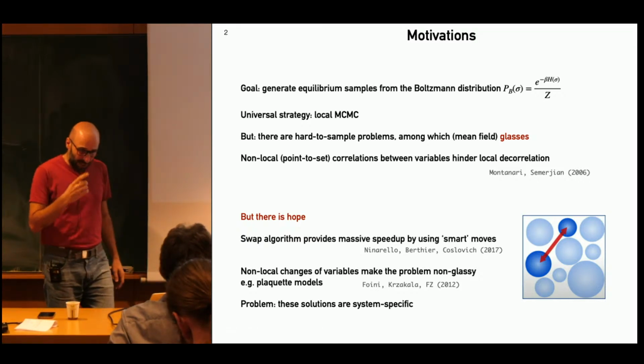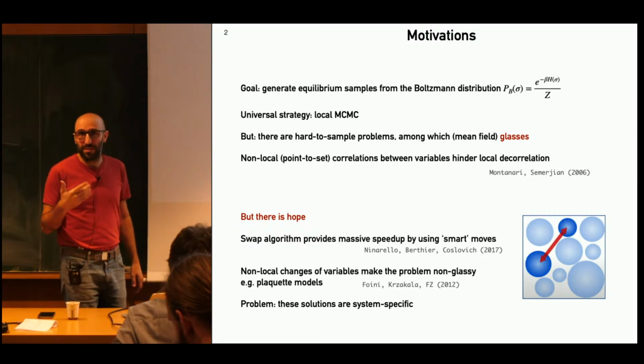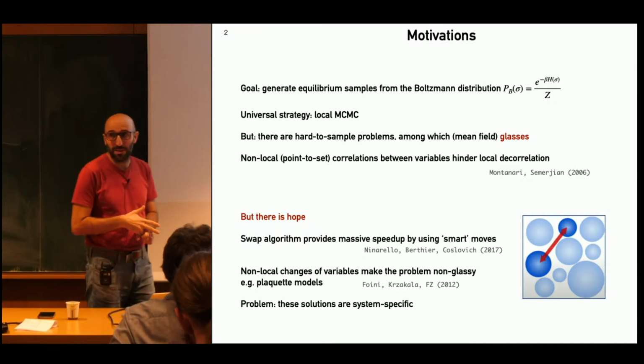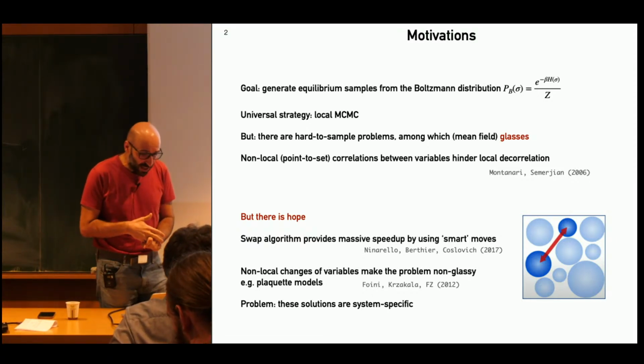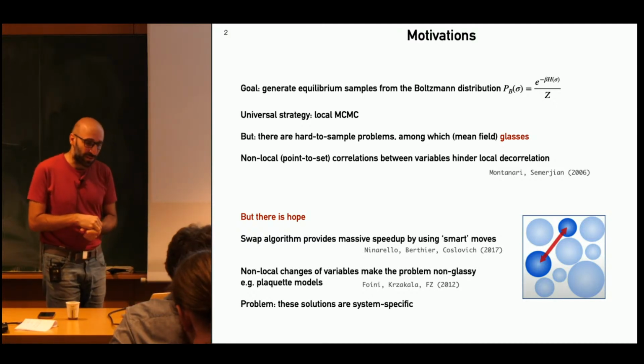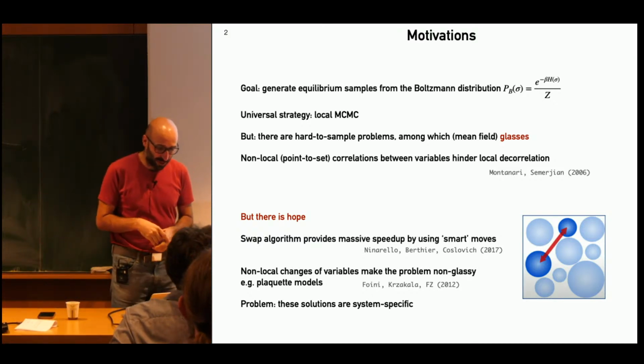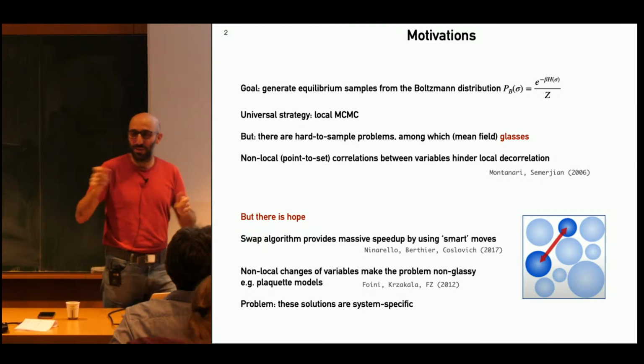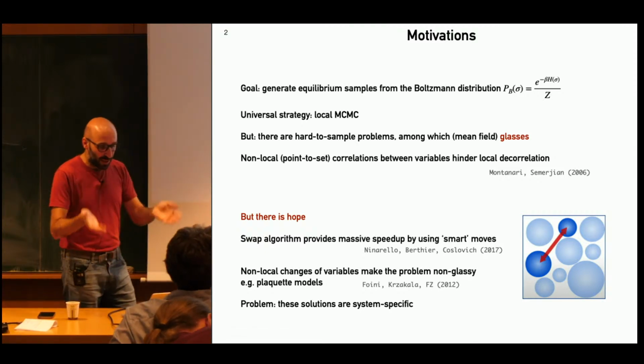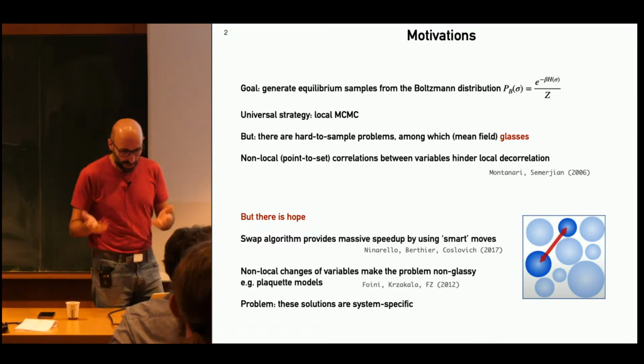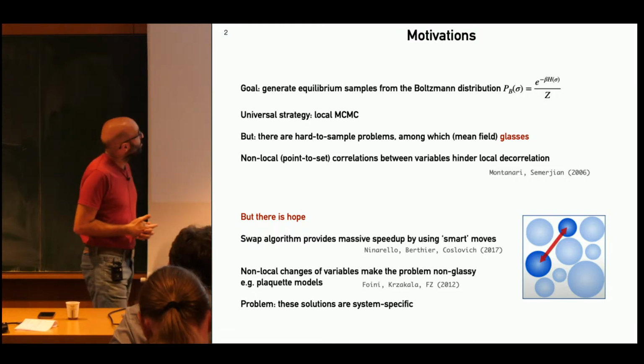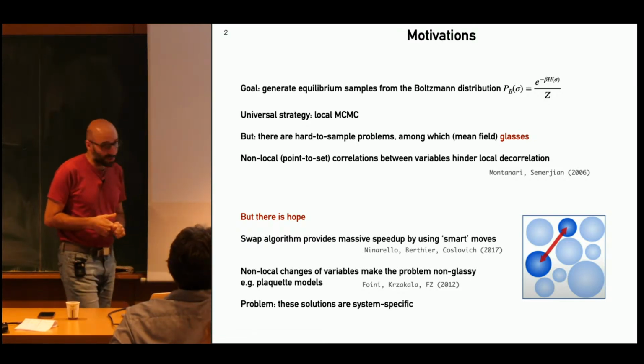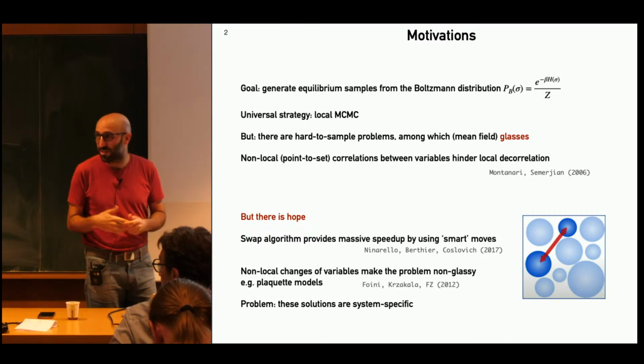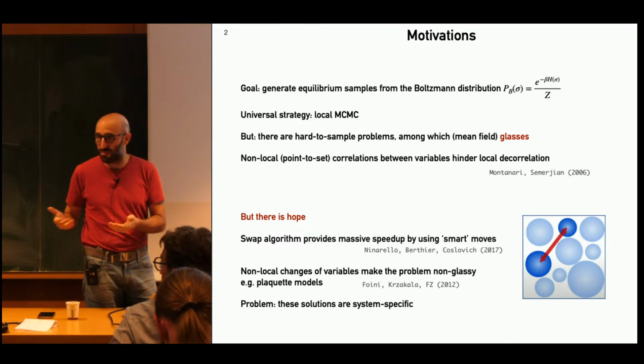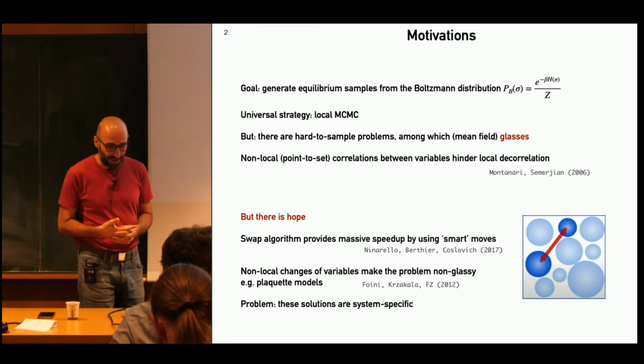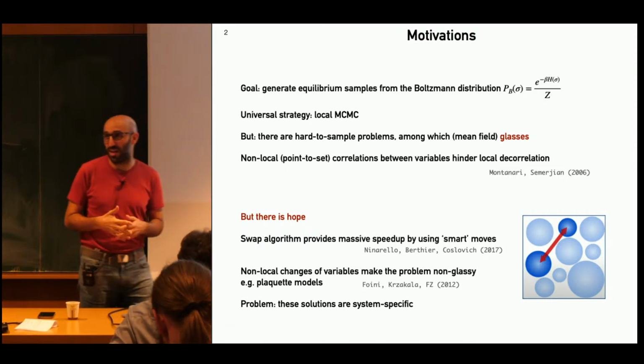So, what's the motivation? The idea is you want to generate equilibrium samples from some Boltzmann distribution. And we know that a universal strategy to do that is to use local Monte Carlo Markov chains. You try to flip a spin or to displace a particle, and you accept the move with the Metropolis weight, for example. Of course, we know that there are problems, in particular glasses, for which this strategy doesn't work very well at low temperatures. The local Monte Carlo gets stuck, and so the problem is hard to sample.